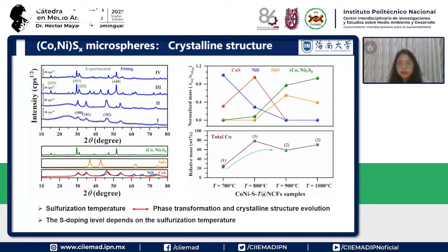But when the temperature increases, there is the presence of nickel oxide. And then when the temperature increases to 1000, there is Co9S8 present. And then we can say the sulfurization temperature plays a key role in the phase transformation and the crystal structure evolution. This is because of the different sulfur doping level at the different sulfurization temperature.